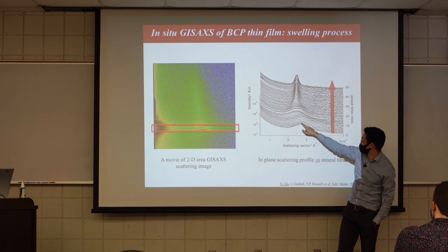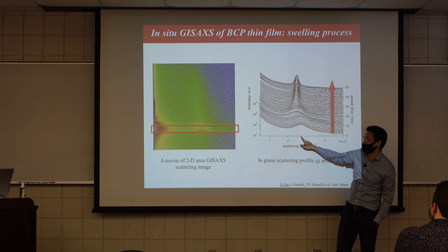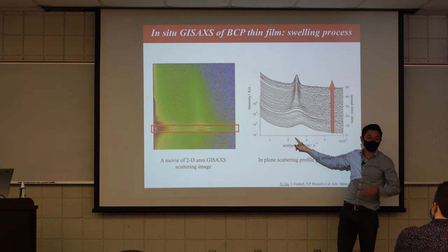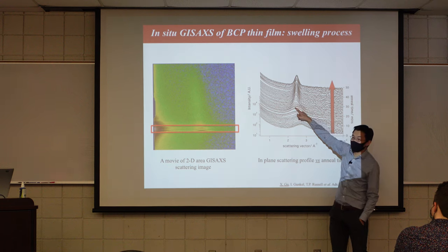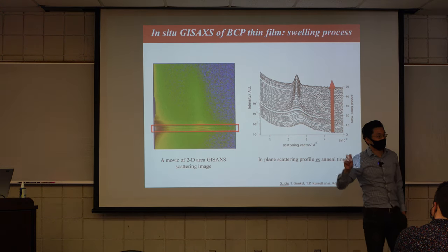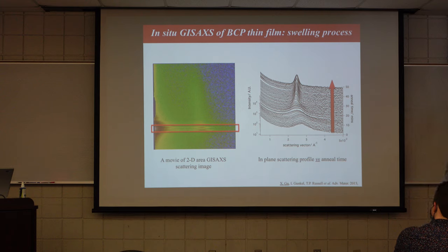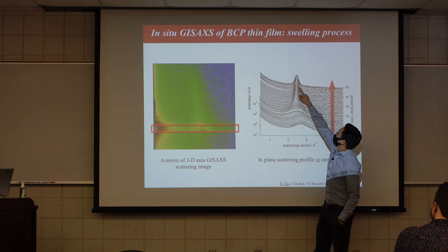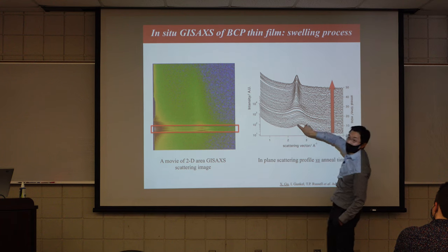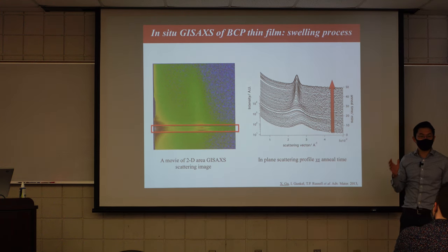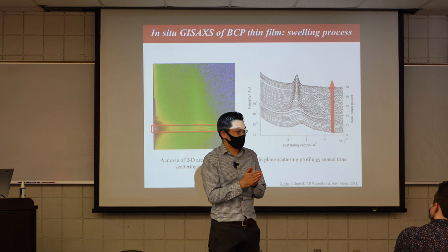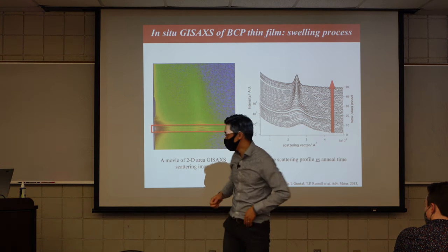And this is on the order of, you can get 2 pi divided by 2.8, maybe about 22 nanometers. After annealing, it's shifted to 2.2. You can do a more accurate calculation, but 2 pi divided by 2.2 is roughly 25, 26 nanometers, okay? So you grow 2-3 nanometers in spacing. More importantly, the width of the peak at half maximum also shrinks quite a bit. Let's see, the last data is here. It's much narrower compared to where we start off. And we know why, because the AFM image already told us that the ordering is much better after we anneal it, so your peak sharpness should increase.